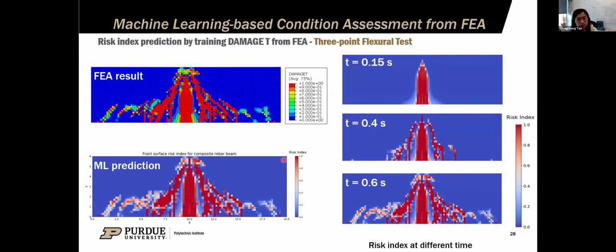So first, we want to predict the potential risk of the reinforced concrete beam in the 3-point bending test. As mentioned earlier, we use damage T data to represent the crack pattern and get the crack propagation over time. Here we apply the damage T data from the FEA to train the machine learning algorithm, and then the machine learning prediction matches quite well with the finite element analysis. From the machine learning model, we can predict the condition of the beam at different times and different locations and give risk index maps accordingly.